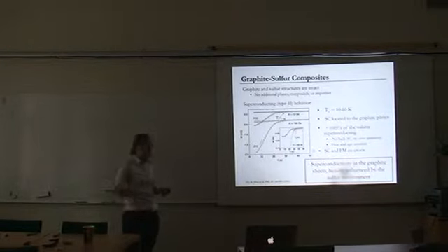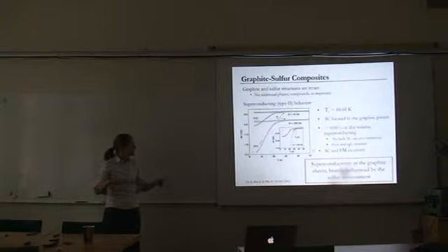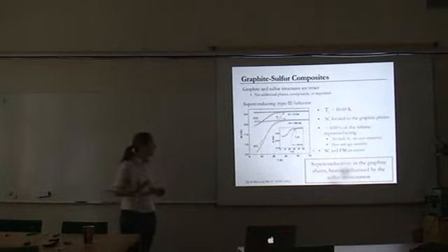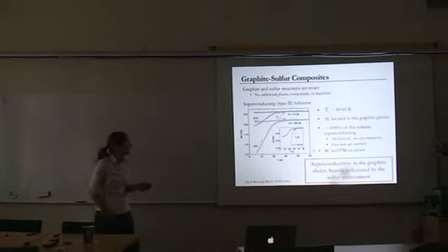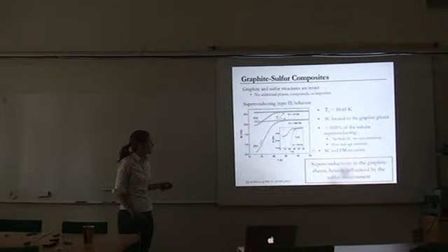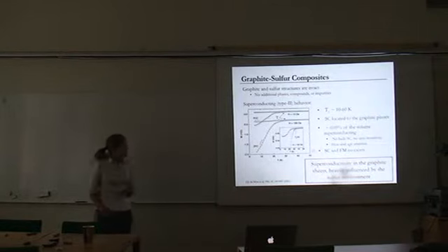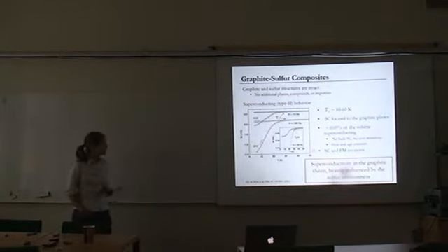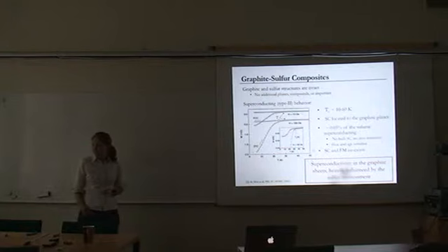They also conclude that superconductivity is localized to the graphite planes, but it's a very small volume that's superconducting. This is a very clear sign of superconductivity, but you don't have any zero resistivity, so there's no bulk superconducting state. It really seems to be an interfacial state that's located on the graphite side. And I'm not showing that here, but it turns out the superconductivity and ferromagnetism actually coexist in some of these samples. Why is it always so small?